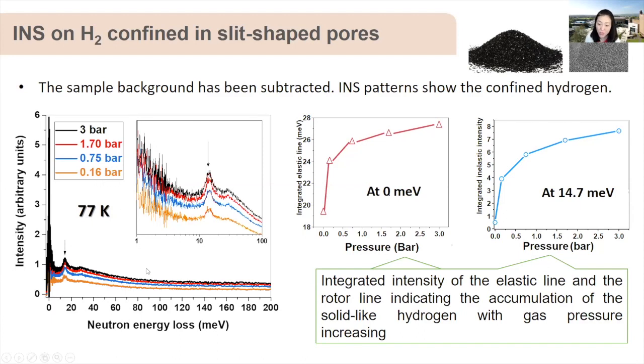And remember, to achieve solid hydrogen in bulk, we need to cool down the whole system to 12 Kelvin, using, for example, liquid helium. But in this case, by applying our material, we can achieve solid-like hydrogen at 77 Kelvin, liquid nitrogen temperature. And that is a much cheaper and easier condition for practical use. The right two figures are the integrated intensity of the elastic line and the rotor line, indicating the accumulation of solid-like hydrogen as gas pressure increases.